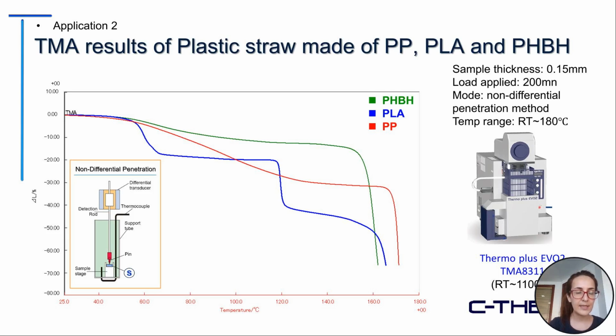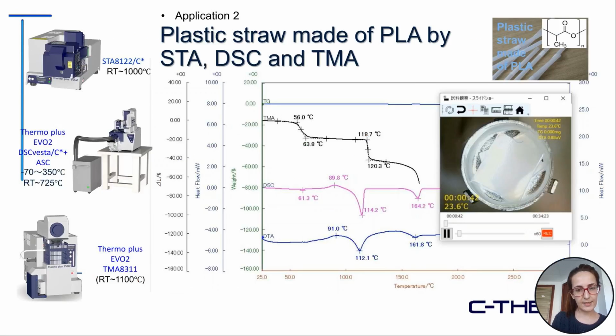In the TMA data, you can see the softening or shrinkage of the samples. The PHBH is much simpler. We have just one single softening, and then it melts at around 160 degrees Celsius. The PP has the same trend, with one softening or shrinkage, and finally it melts at around 170. But the PLA is much more interesting because we can see three softenings or shrinkages in the TMA results. The first softening is related to the glass transition temperature of the PLA, followed by the second one, and finally we have the melting temperature of the PLA at 160.